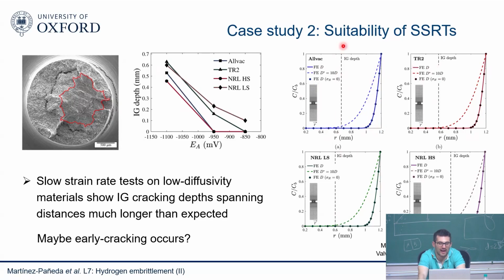So they see that hydrogen has embrittled all of this distance, here all of this distance, all of this distance, all of this distance. But when you plot the hydrogen concentration, you can see that it doesn't get any farther than there. First of all, you may need a minimum hydrogen concentration to embrittle things, so maybe your minimum is somewhere here, I don't know. But not only do you need a minimum, it's basically 0. So how can this happen, right?